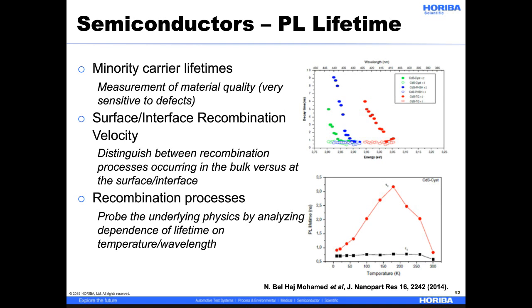An example of a dynamic process within semiconductors that can be probed using TRPL is minority carrier lifetimes. This corresponds to the time between the initial creation and recombination of an electron hole in a semiconductor. The longer the lifetime is, the better the material. TRPL can also provide information on the surface recombination velocity, or the rate at which the minority carrier moves towards the surface to recombine. One can also use TRPL to probe recombination processes happening at the surface versus in the bulk material by varying the wavelength used for excitation, where longer wavelengths correspond to greater absorption depth.